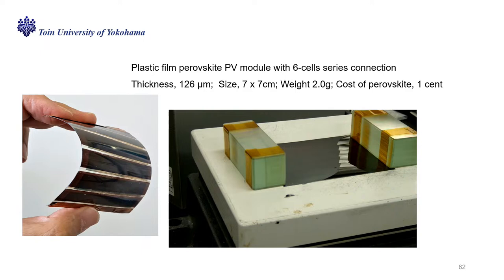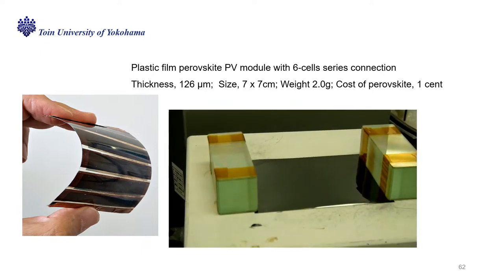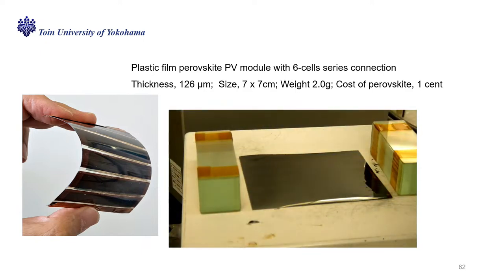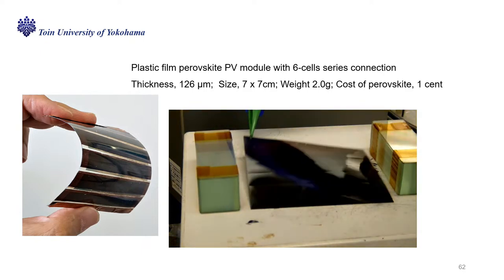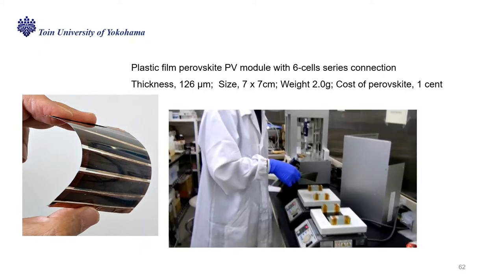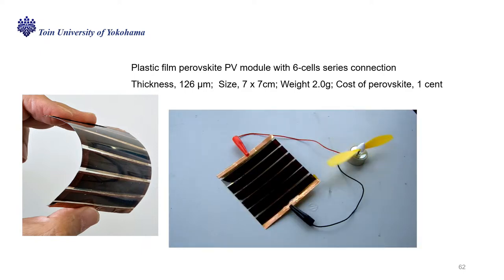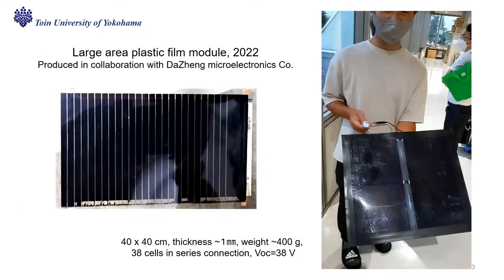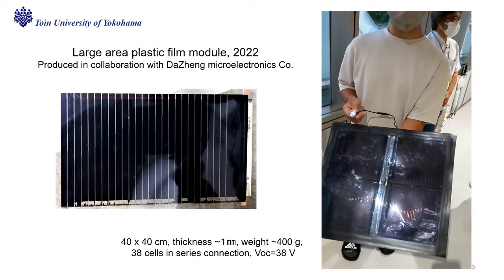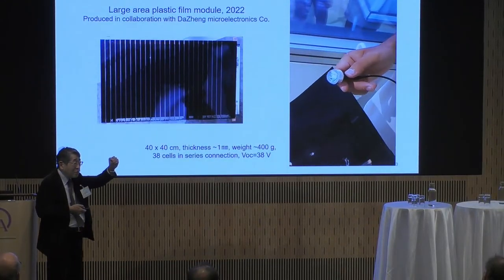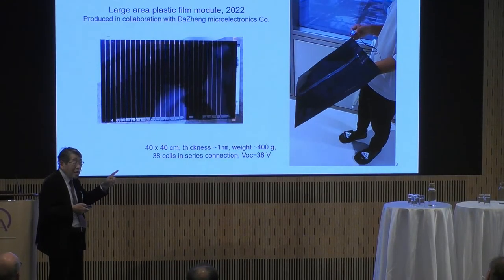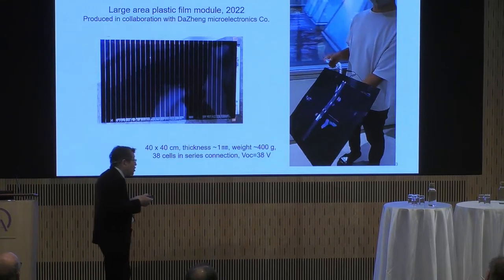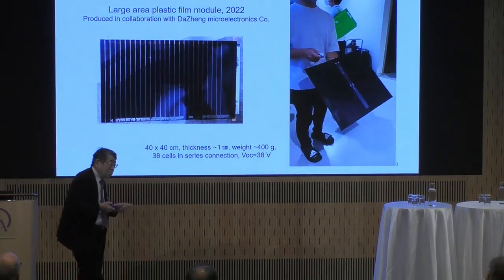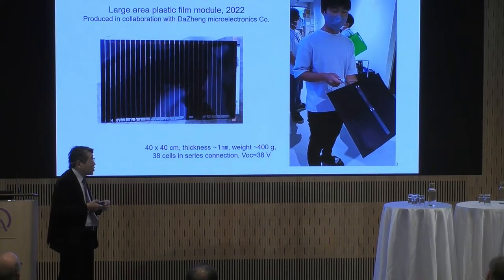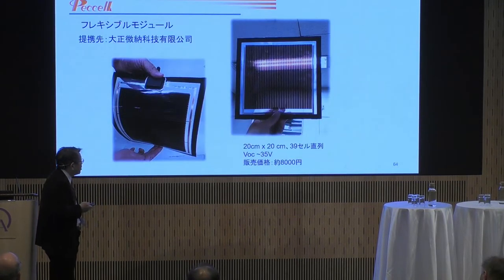The silicon solar cell needs 1,400 degrees Celsius, taking more than 4 hours. But perovskite, the film making is very, very quick, and also low cost. So in China, now, also only one company is using this large module. Yeah, this is a China-made large module, thickness is 1 millimeter. But efficiency is still low, 9%. So we believe we Japanese engineers can make a much better efficiency module by using the technology of Japan.